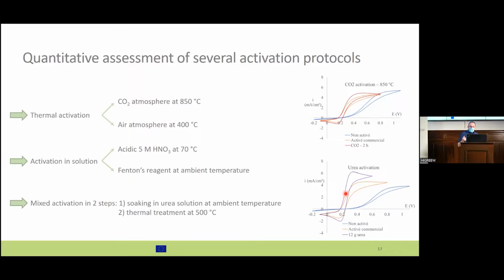So now we have a good method for activation. We tested different activation protocols. Some thermal activation under CO2, under air. We do some activation in solution. We do some activation reported in the literature using urea in order to introduce some heteroatoms. And here is some illustration of this activation.